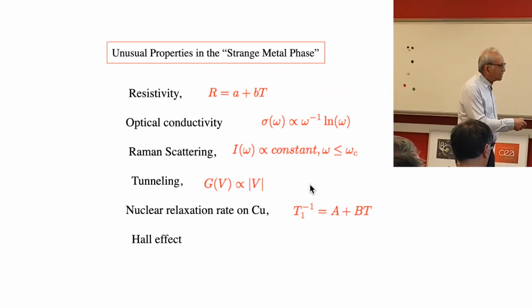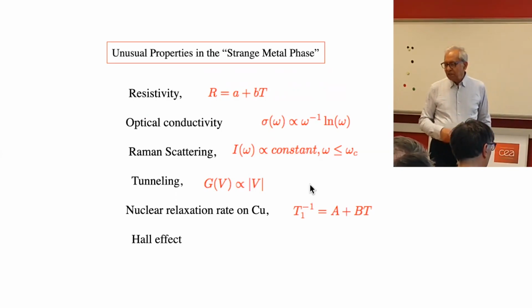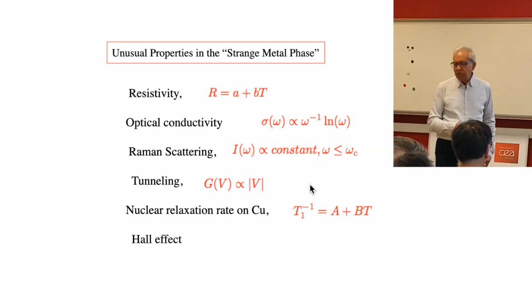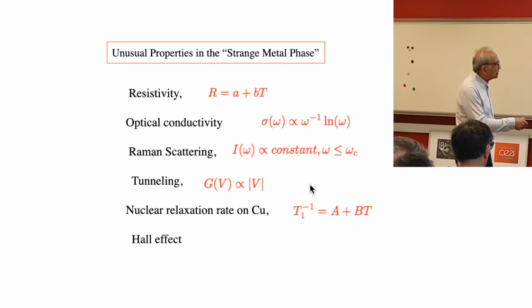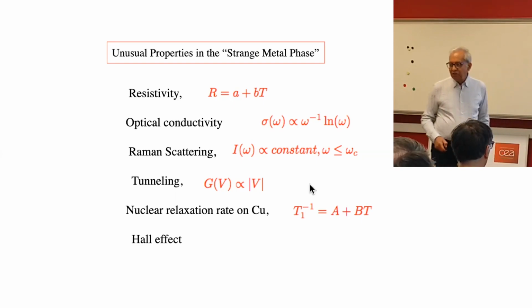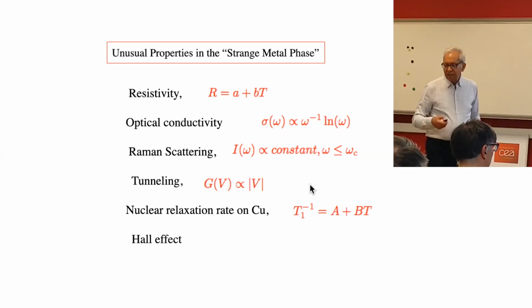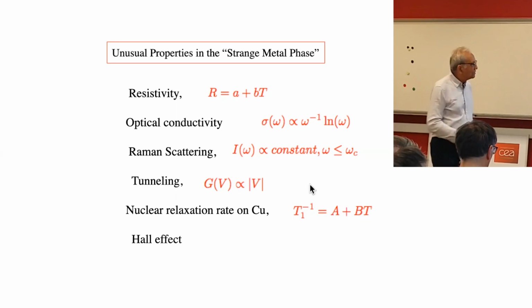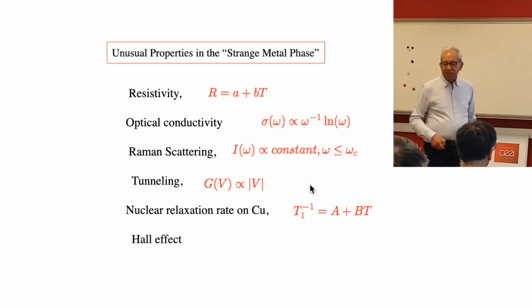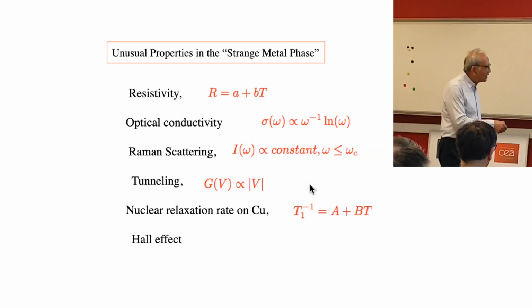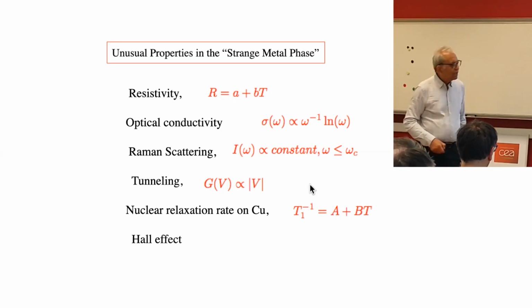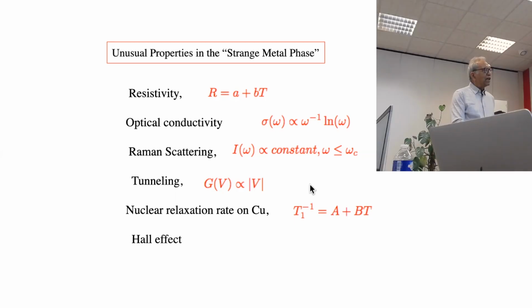Corresponding to that, there is a conductivity which I've grossly sketched, removing the impurity component, goes as 1 over omega log omega. There's a Raman scattering, which goes essentially as a constant up to some energy. The tunneling conductance goes as modulus of voltage. There's a nuclear relaxation rate on copper, which has a leading term that goes as a constant. Now, there are some peculiarities of Hall effect.